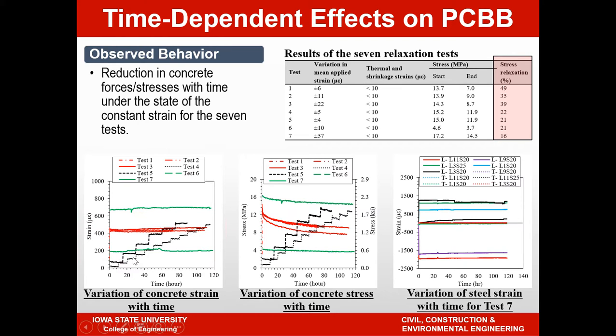Purposely, in these two cases, we applied the initial stress in steps because this is what a typical column would experience. In a gradual fashion, the strain buildup will take place, but yet one would expect some losses in the stresses because the relaxation takes place. So the left-hand side shows that we managed to maintain the strains as constant as possible.